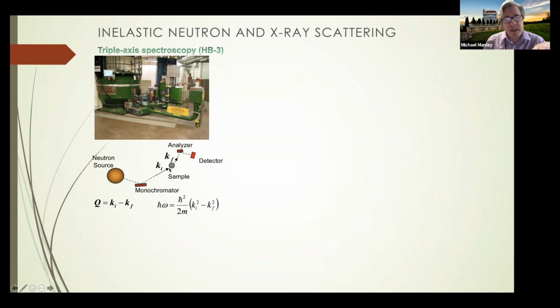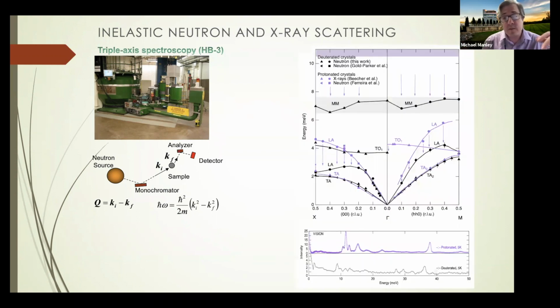But you can pick an incident wave vector that scatters off of your crystal, to scatter in every direction. But what you do is you have this analyzer crystal on the other end, and that allows you to select a final wave vector. And between the two of them, you can scan energy at a fixed position in reciprocal space. The key point about neutrons to recognize here is the reason that this works so easily with neutrons is because neutrons simultaneously have wavelengths of order the spacing of atoms when they have energies on the order of the energy of vibrations, a few millielectronvolts.